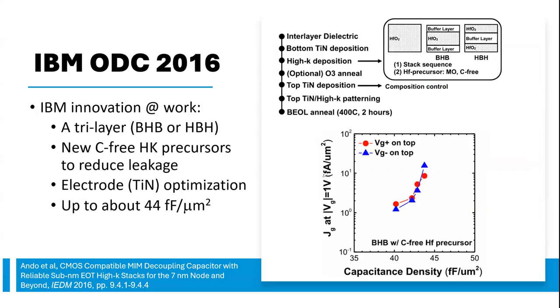So this is what they achieved, right? Going to about 44. I found this figure, 44. Of course, a little bit higher leakage, but if you do a low one, about 40. About 40. And they used titanium nitride optimizations. And they used new carbon-free high-K precursors. I think it's hafnium oxide here. There's a buffer layer up and down.